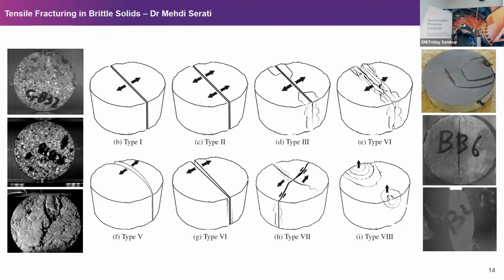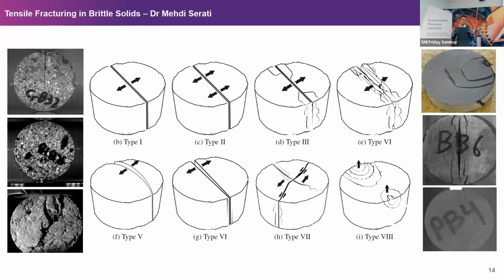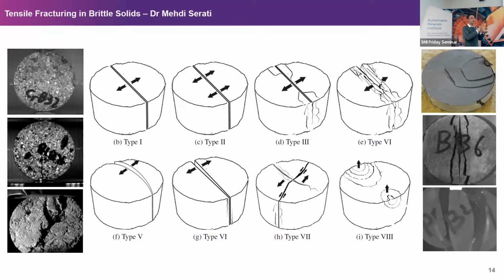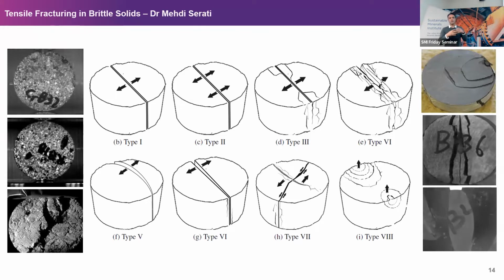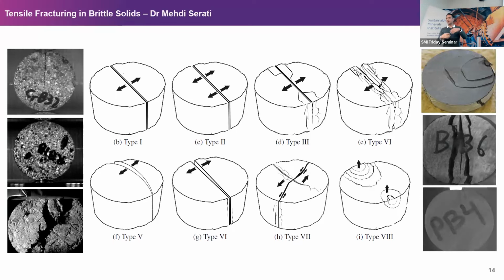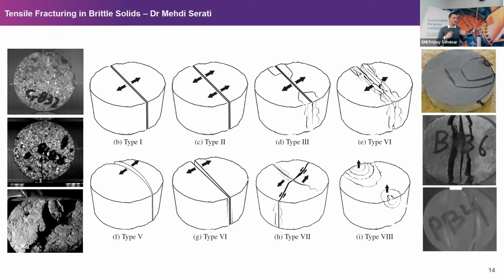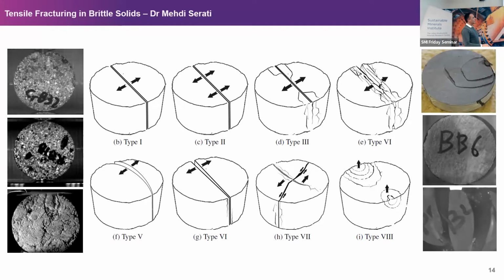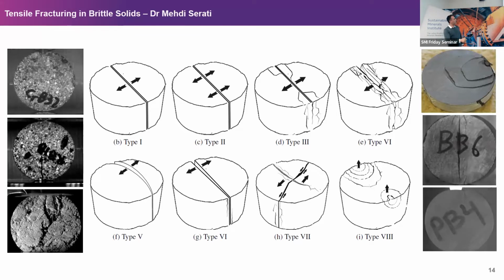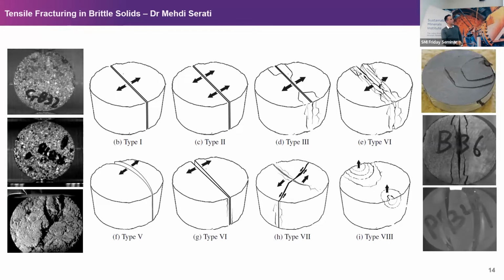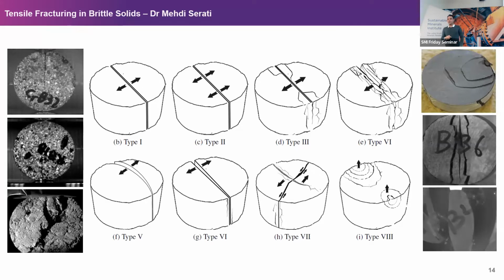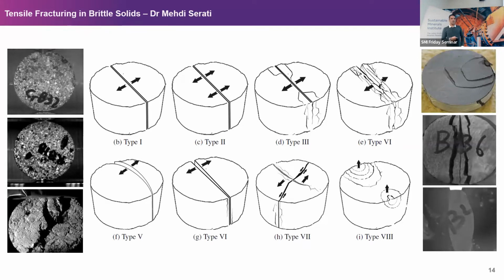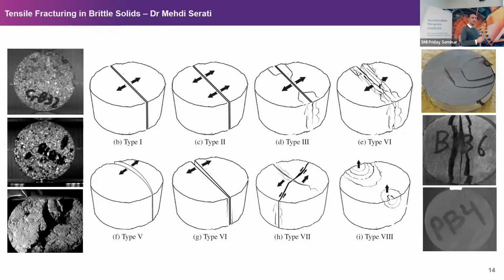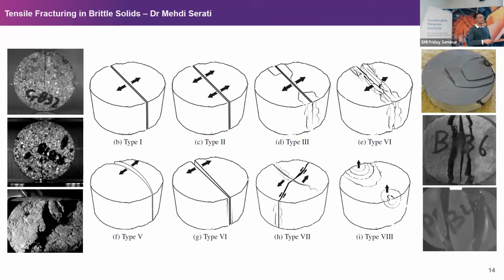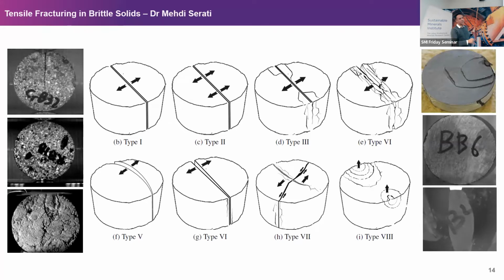So we did not play with the size, we did not play with the rate of loading. We always followed the ISRM recommendations in terms of the grains, like the size of the sample is 10 times larger than the grain size, and you know, the standard requirement. But basically what this study suggests is that, especially for hard rock, like this is a PMMA, and I've got some other examples for ceramic that I also showed you in the previous slide, no matter how hard you try, as long as you are following the standard, there is no way that you can get that single crack.